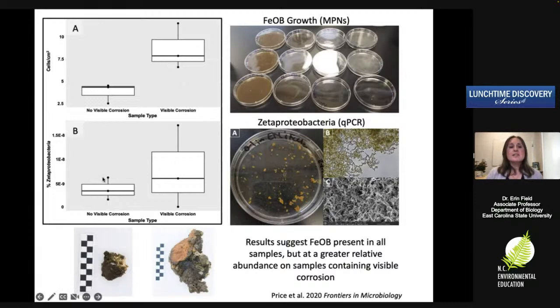And what we found is, again, we find them in all the samples, but they're not in as high relative abundance as the just general MPNs were. So you can see what that means is, see how this box is much wider than, say, this box up here. So this means that we may have missed some of them. So the zeta proteobacteria are a large proportion of our iron oxidizers, but we don't think it's all of them. So we think there's some more in there that we just haven't identified yet. So we'd love to do that. I can't wait to see who they are.